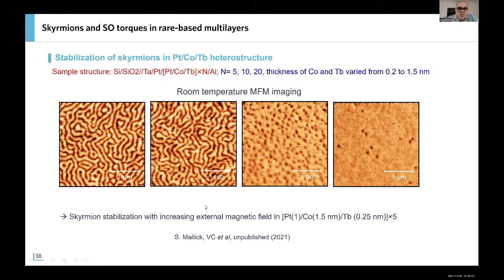So there has been a huge work of development of some specific tip to realize this image, but you do see that small skyrmions in the range of 100 nanometers or less can be stabilized in these multilayers.